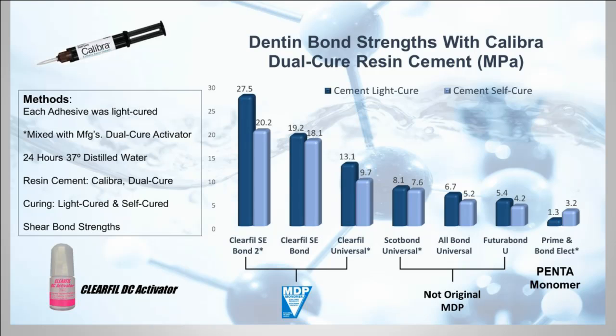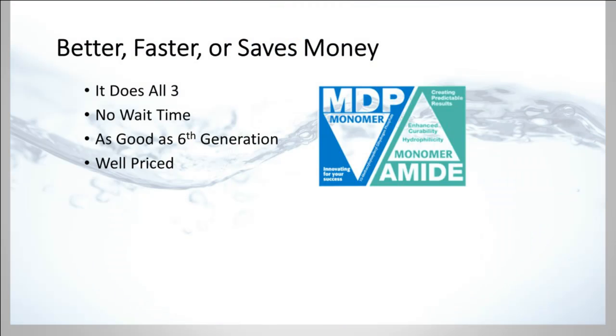And so let's look at the dentin bond strengths with Calibra. And this is a dual cure resin using MPa, the megapascals. Let's look at this. So we have the original MDP strengths here in the Clearfil SE Bond 2, Clearfil Bond, and Clearfil Universal Bond. And so you have the light cured and you have the self cure. So light cure and self cure, light cure, self cure, and then look over here, not original MDP, and look at the values where they drop off. Then you have the pentamonomer. I mean, this is just, that's terrible, 1.3. So you can see there is value in this with the original MDP. Again, here the asterisk means they put the Clearfil DC activator in it, or the one from their company in it to get those bond strengths.